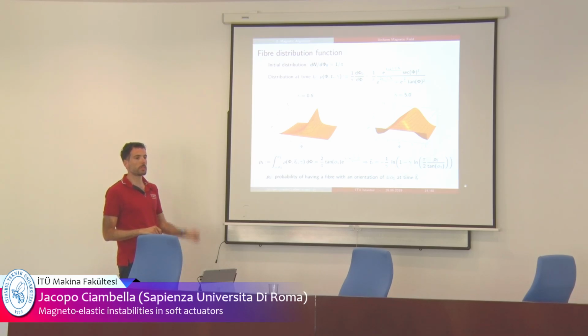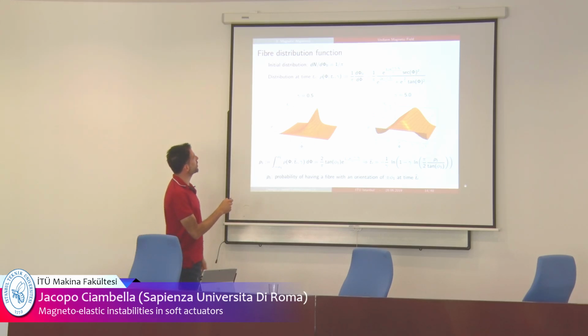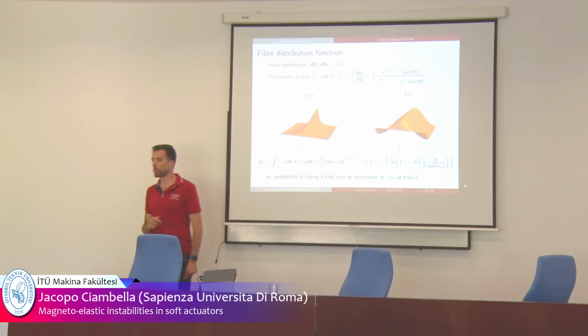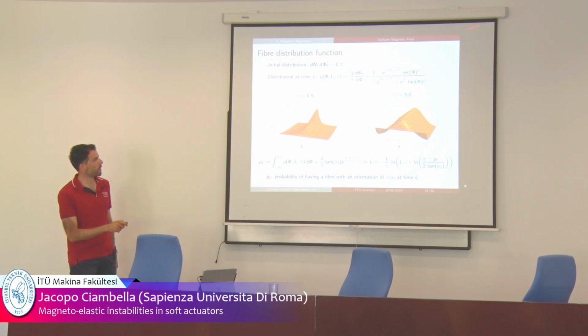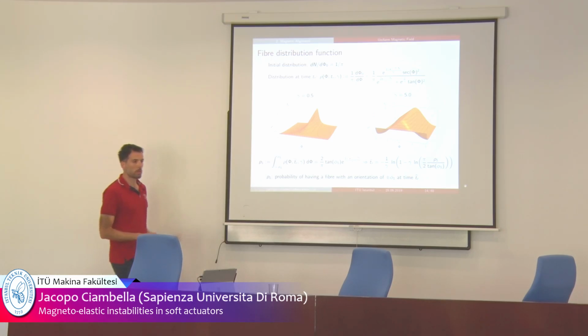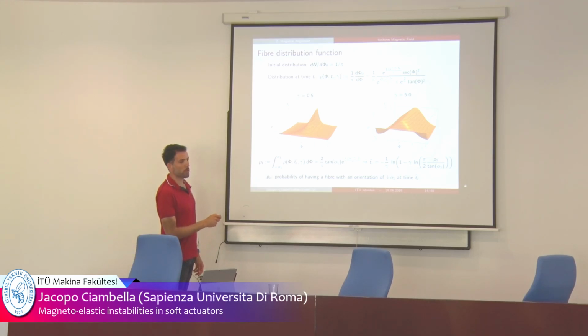You can also work out how the distribution of the fibers evolves with time. If we assume that you have an initial distribution which is uniform, 1 over pi, meaning a uniform distribution at time 0, we can work out the distribution at time tau r. You end up having this expression here, which is plotted here. On this axis, you have the particle direction, c, which goes from minus pi over 2 to pi over 2. On this axis, you have the time. You start with a uniform distribution, so all angles are equally probable.